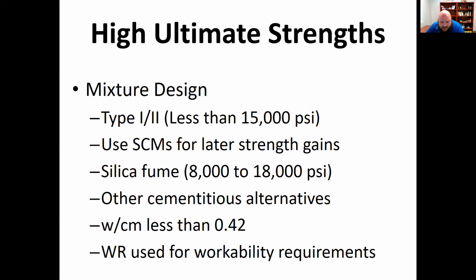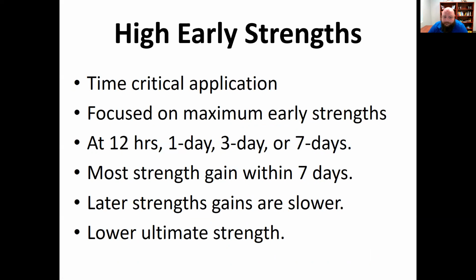You're going to see a lot of times the water cement ratio that's well below 0.42. And so just realize that there are going to be water reducers used to meet the workability requirements, especially if it gets to be self-consolidating. You're going to be using a lot of mid or high range water reducers, aka superplasticizers, super Ps, whatever you want to call them. But you're going to get something like that so that you can get the workability you need.